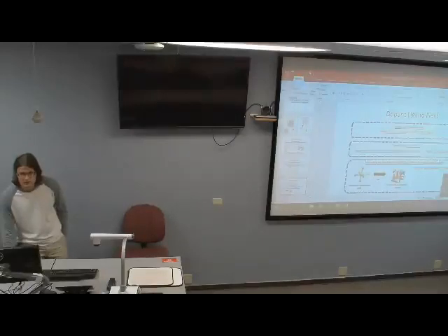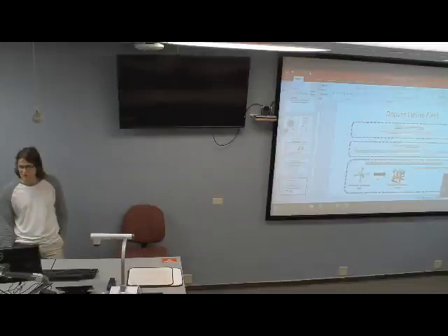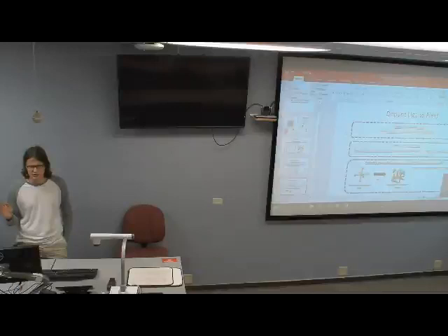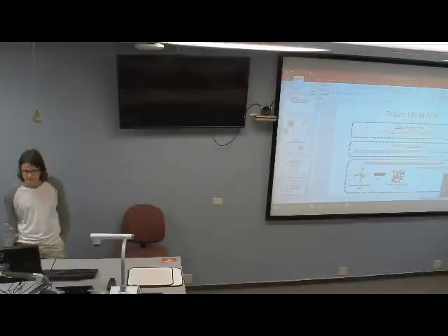And what kind of theory have you been using for this? Oh yeah, so this is all DFT, and we're using the PBE functional for all the molecular dynamics. And then all the trajectories are roughly 1 picosecond, with 1 femtosecond time steps.